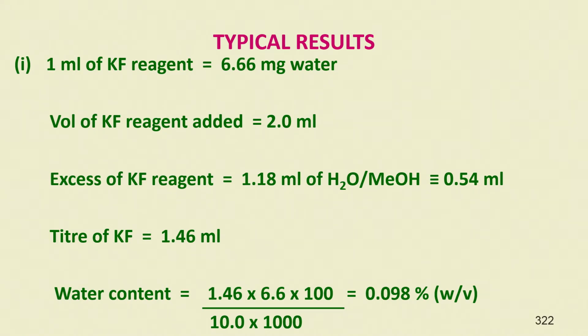Now, how much is consumed? That is 0.54 ml. So, the titer value I got is 1.46, that is 2 ml minus 0.54. So, the water content I can calculate: 1.46 multiplied by 6.6, and this 100 comes from percentage. To calculate the percentage, this 10 ml is the volume of the sample and 1000 is the per liter, to convert milligram into grams. So, if you do everything according to this calculation, you will end up with 0.098% of water, weight by volume percentage.